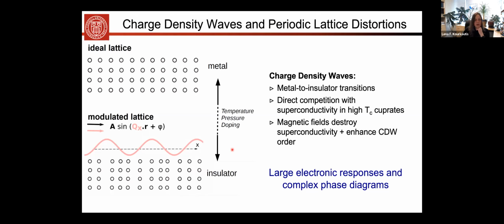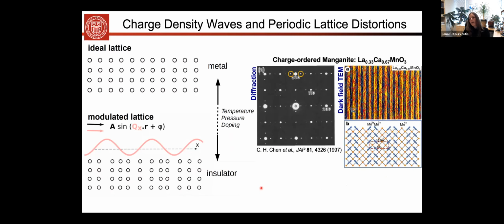And what we will be doing for now is using the lattice as a metric to probe our charge-ordered phase. Now, as I mentioned before, electron microscopy has been used for these charge-ordered systems before. So this is a charge-ordered manganite that was studied in the late 90s. First in diffraction, where you'll see superlattice peaks that decorate the Bragg spots of the lattice. And these superlattice peaks can be used to image the ordered phase in our manganite system. And these are the famous stripes in the stripe-ordered manganites that were imaged using dark field TEM in the 90s.